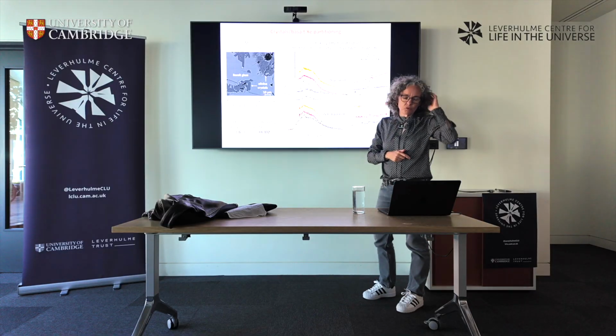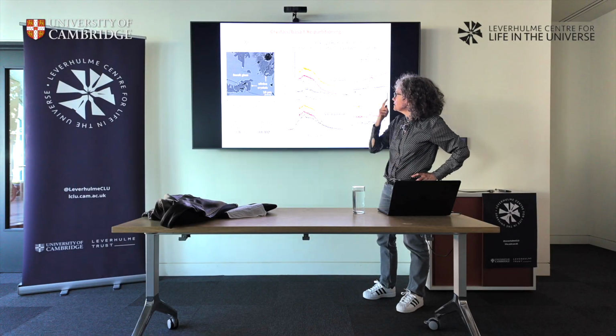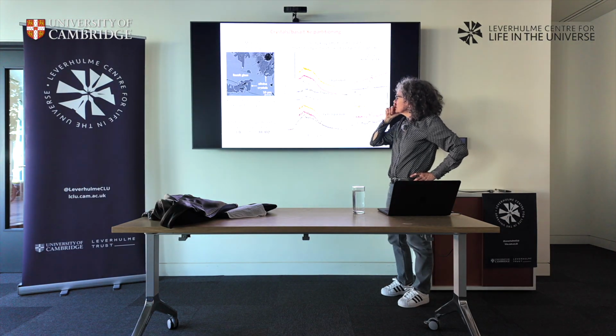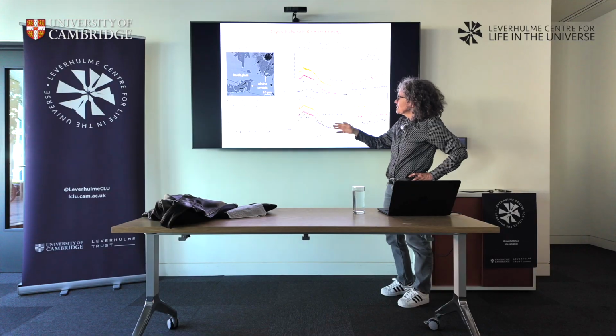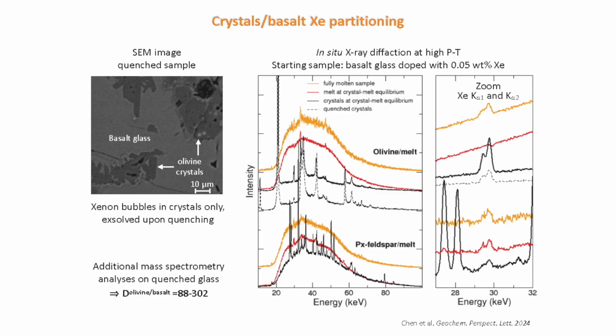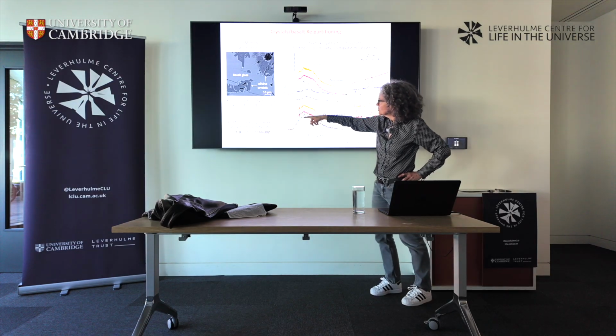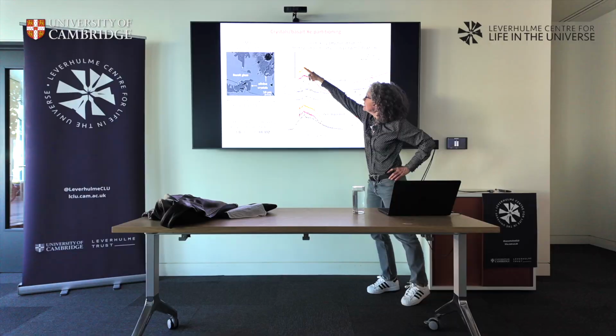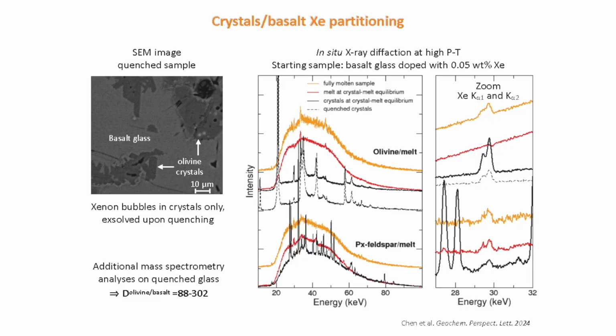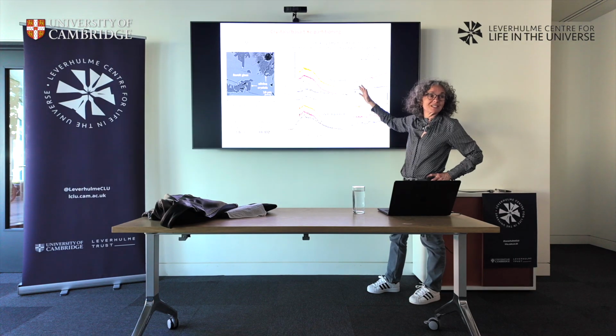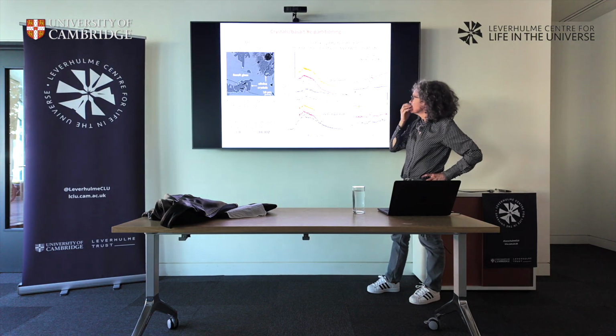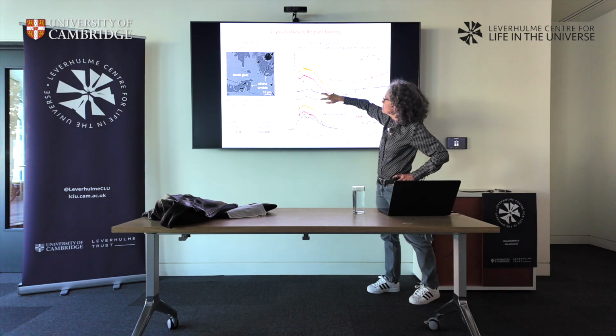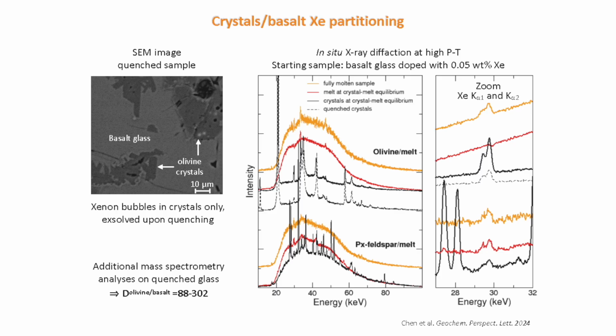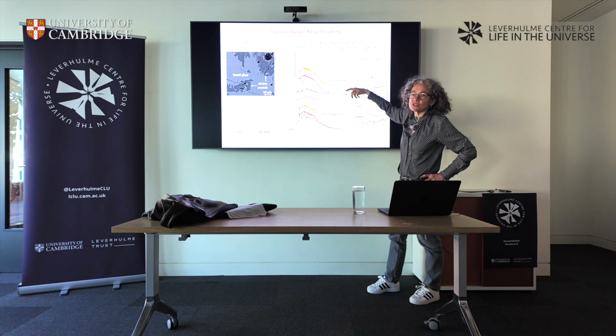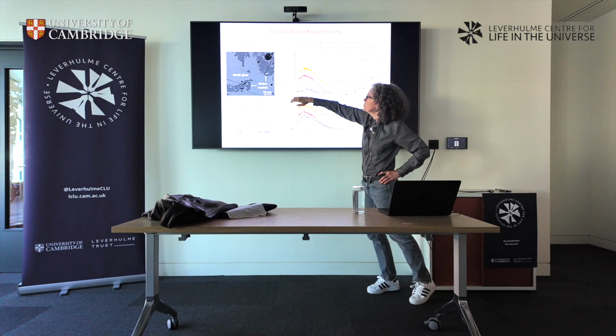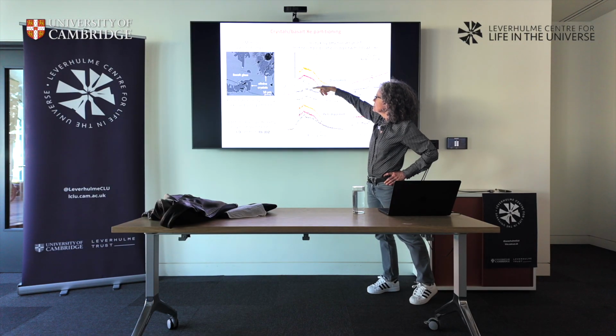So what we did is that we tried to measure that in situ. We did that at the US synchrotron, where there is a nice press where you can do diffraction, but it's energy dispersive diffraction, meaning that on this spectrum, not only do you have diffraction peaks, for example for the crystals, but if you zoom, this is a zoom here, you also have the fluorescence peaks of xenon. So you have both the Bragg peaks from the crystals and the fluorescence from xenon in the same data set, which is nice. In this case, the crystals are the black curves, and when you melt, the baseline increases because the melt has some diffuse scattering. So you know it's molten because you lose the Bragg peaks and you observe this diffuse scattering. So you know where the melt is, you know where the crystals are.